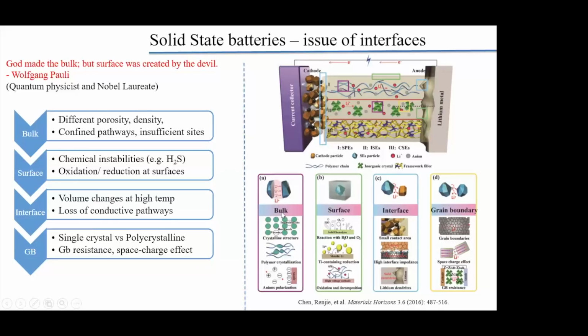So, we spoke about bulk. At the bulk, you have porosity. For example, if you use polymer, then it should have the right kind of porosity, density, and crystalline structure. At the surface, there should not be any inadvertent oxidation, reduction, or other chemical reactions. At the surface interface, you need the right kind of contact. And then you have something called grain boundary. A single crystal is better than polycrystalline, because the more boundaries you have, the tougher it gets. And that's why single crystal is better. And then there's something called grain boundary resistance and the space charge effect.